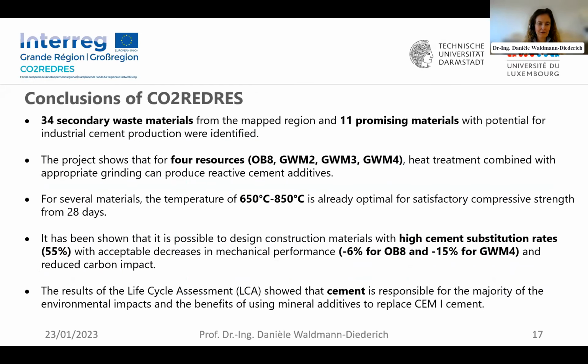Yes, many thanks. So in total, we were able to identify 34 different secondary waste materials, where 11 of these were promising materials with a high potential to be used in industrial cement production. Then out of these, 4 resources showed that they were very interesting in terms of heat treatment combined with an appropriate grinding, so that we really could produce reactive cement additives out of these. Then our calcination temperatures were between 650 and 850 degrees.